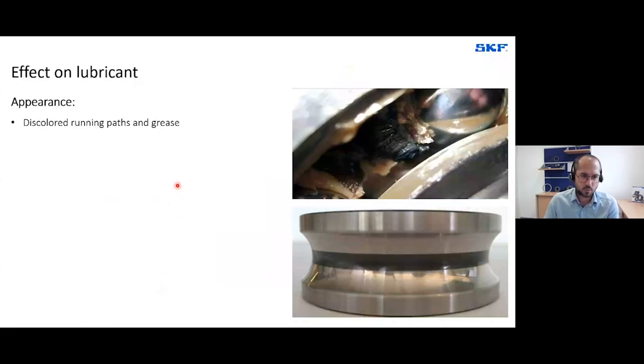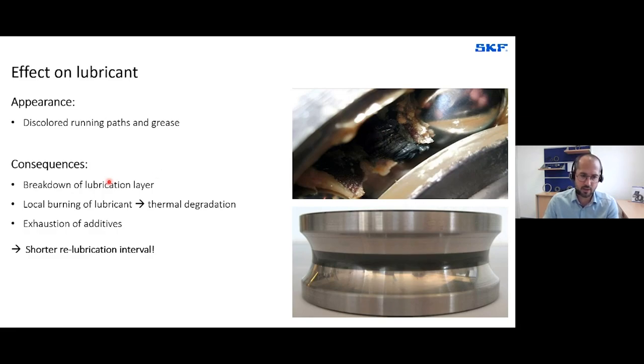Besides the effect on the bearing components, like rings and balls, it also has an effect on the lubricant. When those sparks break down the lubricant layer, you can get discolored running paths or blackened grease. This is how you recognize it. But as I said, it is breaking down the lubricant layer. It locally burns the lubricant, which leads to thermal degradation, and it can also use up your additives in your grease or your oil. So again, it is at least as important as the effect on the mechanical components. It is shortening your relubrication interval or grease life. And in the end, it is shortening your bearing service life.